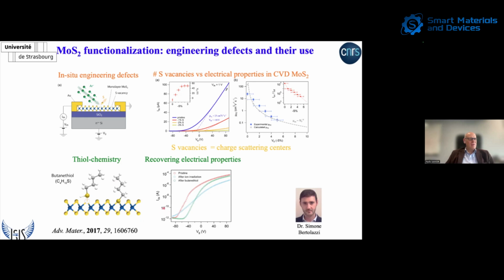And indeed, this is useful as a way to recover to a great extent the electrical characteristics that we lost upon defect formation. But on the other hand, what one is doing is nothing else than grafting a molecular function on the basal plane of the molybdenum disulfide.